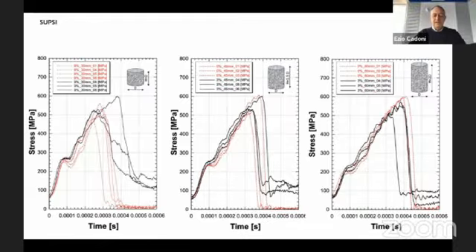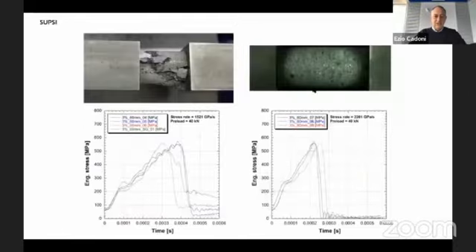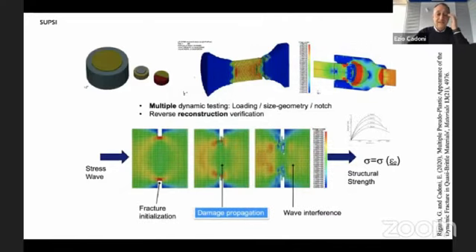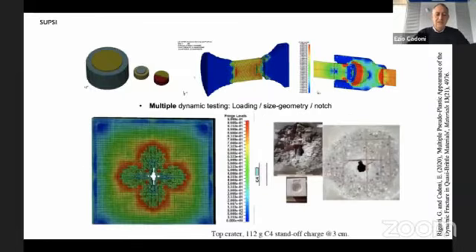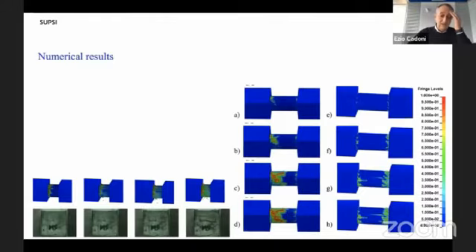We have observed that by increasing the stress rate, the shear failure occurs with a higher stress rate. Thanks to the results of more than 400 dynamic tests, on samples with different size, shape, and notch geometries under different failure modes, a new model was developed. This material model is named DAMP, Damage Propagation Model, where the damage interferes with the wave propagation, and we have considered this phenomenon. This model was used to simulate the blast loading on the sandwich slab, obtaining very good similarity with experimental results.